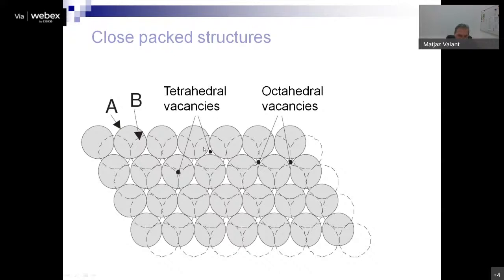We also can see these particular sites in these layers. You see, this is what we call a tetrahedral vacancy. It is a vacancy between three atoms in the first layer and 1 atom on the top of the next layer. Here is the same tetrahedral vacancy, just that the layers are turned the other way around. Then we have here octahedral vacancies, and this is actually the vacancies where we can see through. It's the vacancy between 3 atoms at the bottom and 3 atoms at the top. And it's kind of a see-through vacancy. So we have 2 types of vacancies.